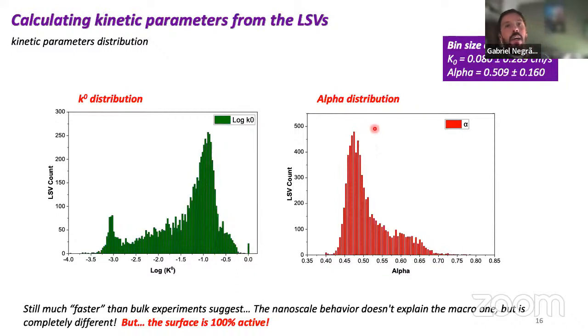So how do we tie that with the heterogeneous accessible electrode model and the behavior we see in the bulk? The answer is that we don't, and that's the biggest problem for us so far. We're not sure how to explain it, because the average K0 that we find from bulk is not exactly this. They differ a little bit in order of magnitude. The other one we expect to be a little bit faster than that. So we're not sure if there's some experimental bias here. We don't think there is. We think we're actually changing a little bit the polarization of the conductivity of the ITO at some point.